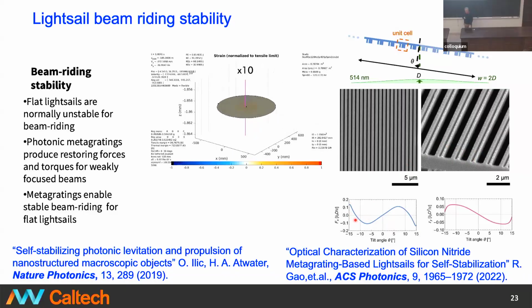And in particular, what we can do is develop relationships between the transverse force or the torque. So the transverse force is the one that is pushing the light sail back onto the optical axis. The torque is the term that is now turning the light sail back onto a trajectory that's perpendicular to the optical axis. So these in-plane force versus angle and torque versus angle curves are the ones that can give rise to a stabilized trajectory. So we developed for thin membranes that are spinning at tens of RPMs, that stabilizes a flat structure. The flat structure, if it were specular, would be unstable, but with metagratings, and this is a full wave simulation that allows us to look at the forces imparted by the metagrating structures, and this was worked out in this paper, we can stabilize and propel a flat structure.